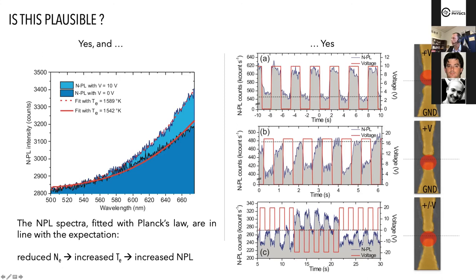So imagine now I'm recording the device here. We have a positive electrode, a negative electrode, a gap here, and the red dot is the position of the laser. In one experiment, we slightly position the laser towards the positive electrode, so we have NPL signal essentially coming from this electrode. In the other experiment, we slightly downshift our excitation spot, so we have mostly light coming from the ground electrode. And in the last experiment, we kept the excitation on the bottom electrode, but we switched the polarity of the voltage. Okay, so let me go through the curves.